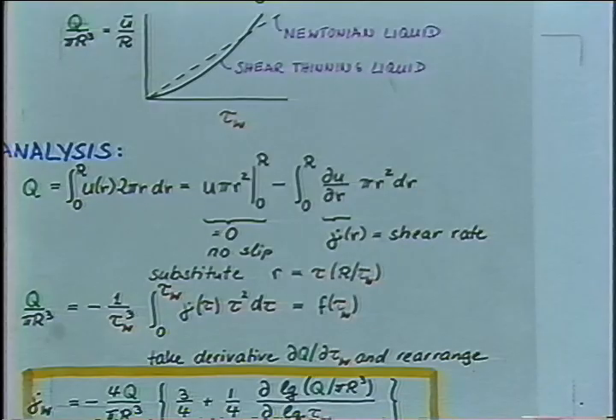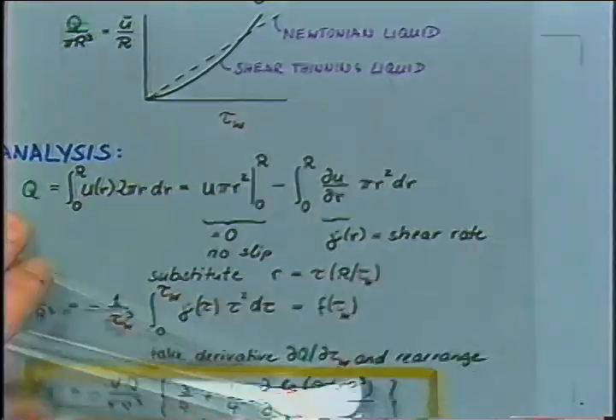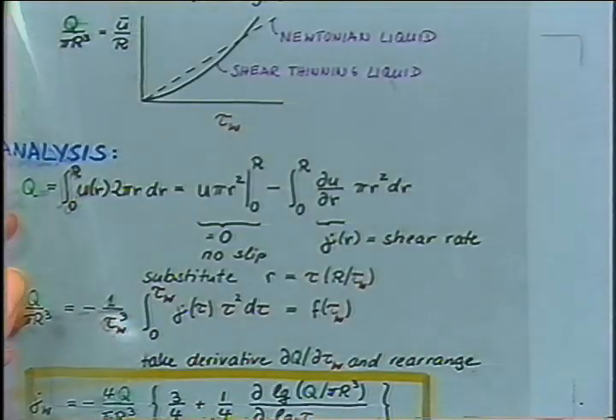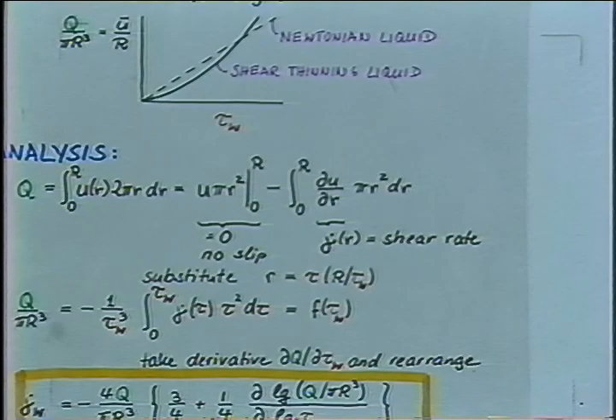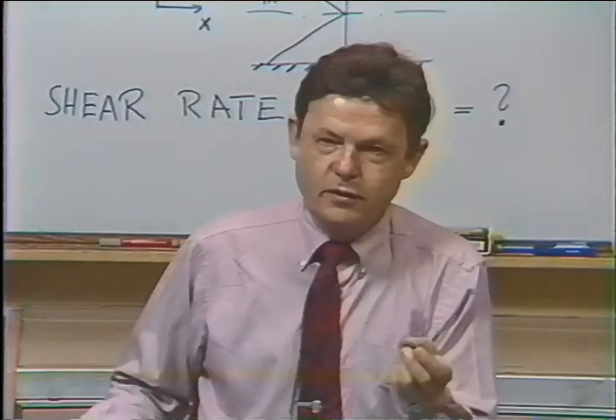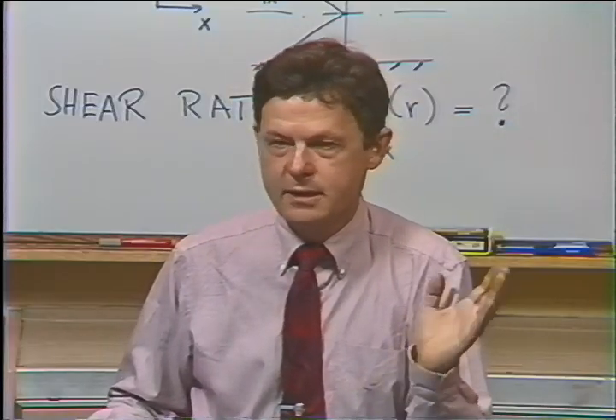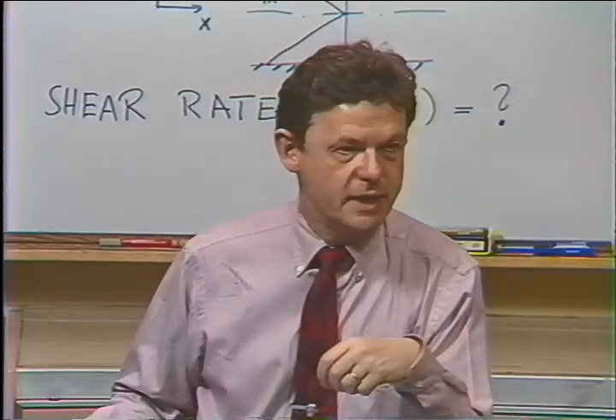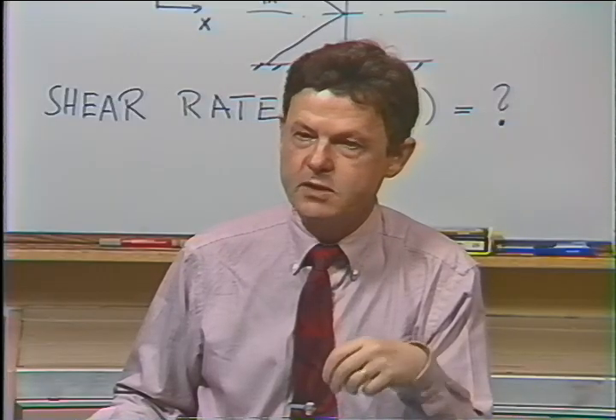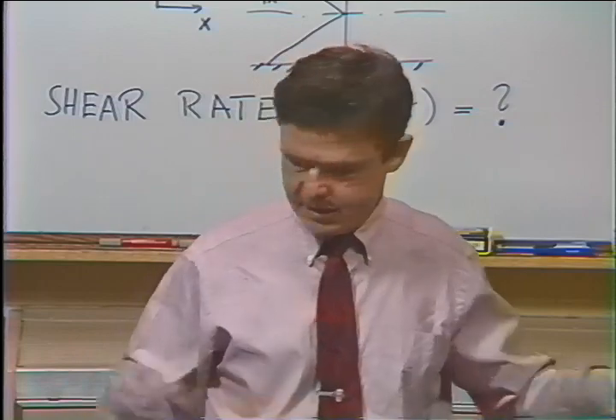So the result of that analysis is the shear rate at the wall, not the shear rate distribution. We only know the shear rate at one position, and that's at the wall. But since we know the shear stress at the wall, we can take the ratio of the two and then get the viscosity for the material element sitting at the wall. Now, we should not take this for granted. We are taking the property of a material element at the wall for characterizing bulk properties. But all experiments seem to confirm that condition, so we don't have to worry about it. So we only have the shear rate at the wall to analyze our experiment.